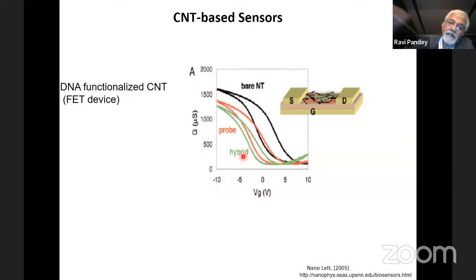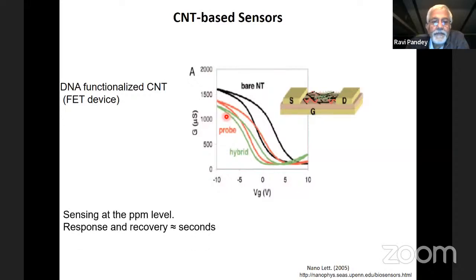And if I bring in my target, which is attached to the probe, you can see distinctly the green part is nothing but the hybrid material, which has the target, probe, and the carbon nanotube. So by looking at the shift in the signal, going from pristine to probe functionalized, and then the hybrid, one can distinguish the sensing capability or the identity of the molecule being sensed. And this ppm level sensing can be done, and response and recovery is definitely in seconds.